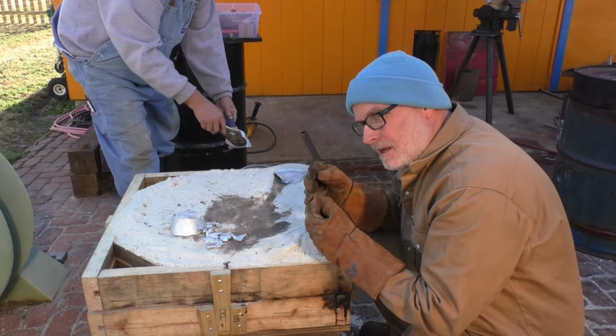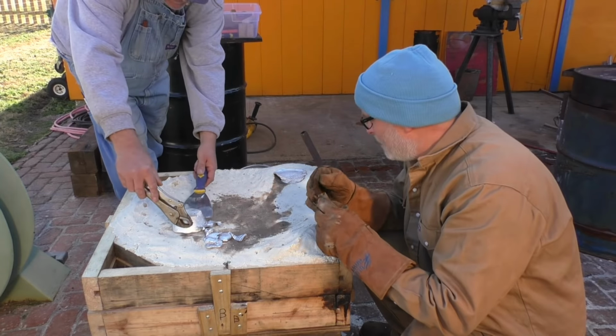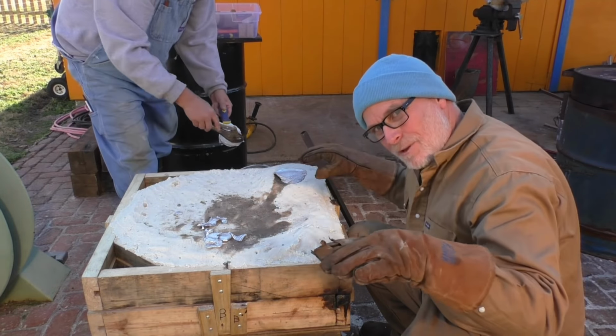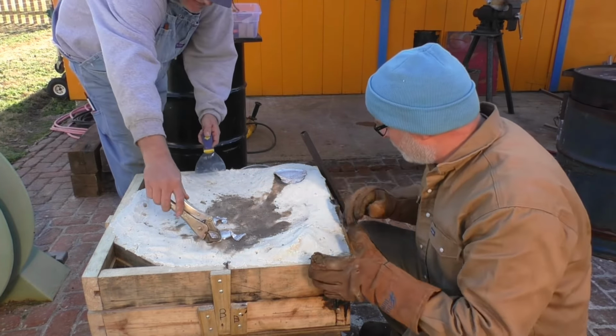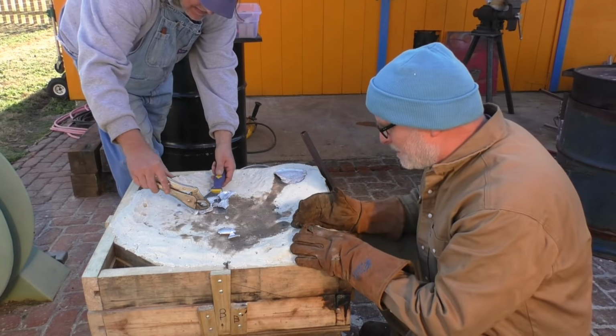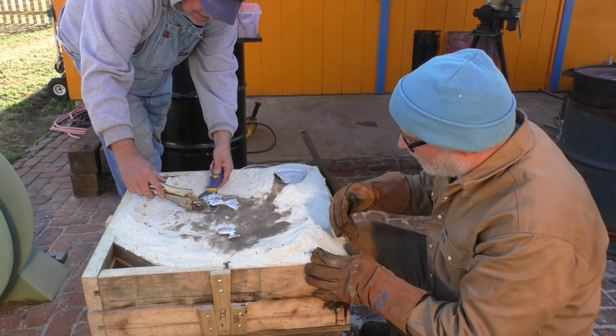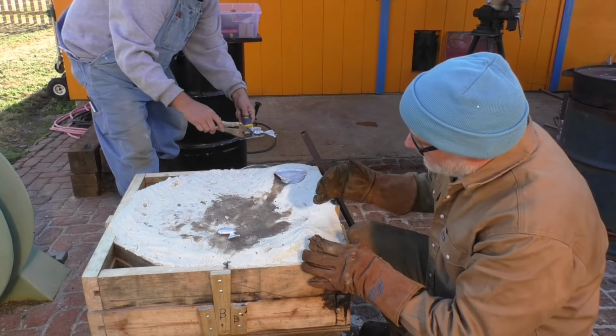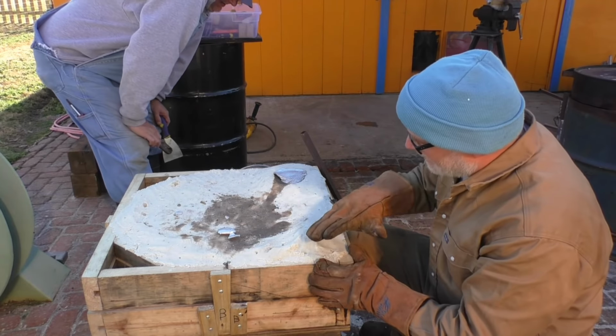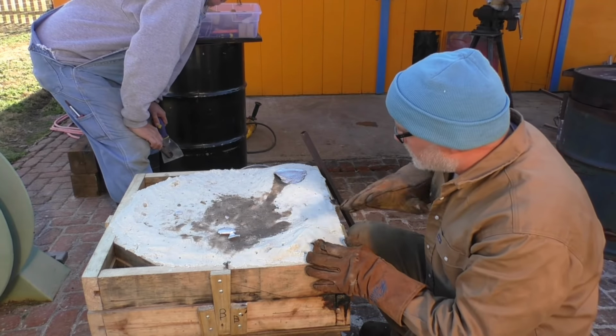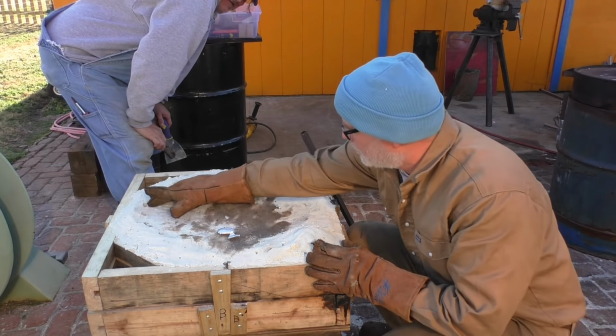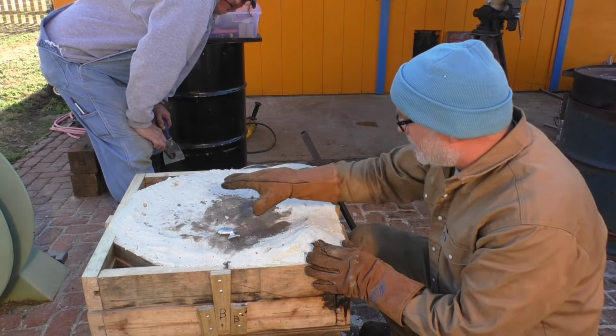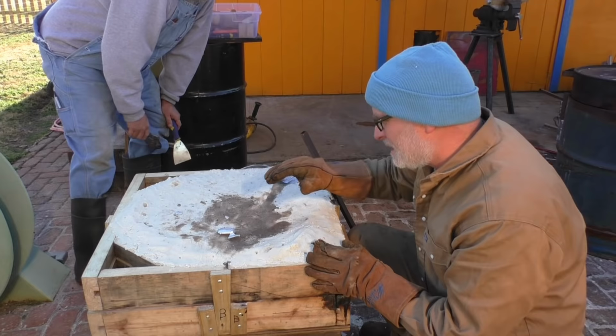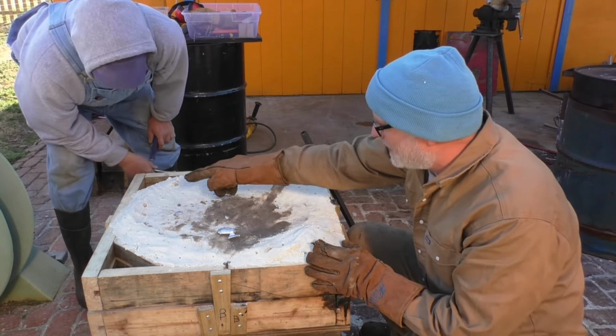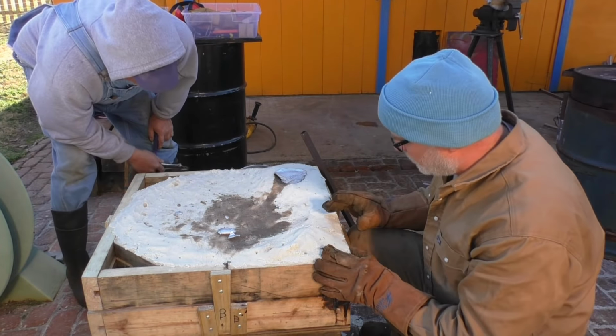And any of the contaminants, the dross that I didn't skim out, will float to the top and it will stick to that runner. I learned that from a foundry here in town. Then it gets to the riser and it goes down into the bottom part of the riser first. And any heavy sand or crap will stay down there in the bottom. Then it floats up and it starts going across our part over to our 3 vents. And it didn't come out the vents, which is perfect because at this temperature it should just rise up them a little bit and we can actually look down in those holes and see a little bit of aluminum.